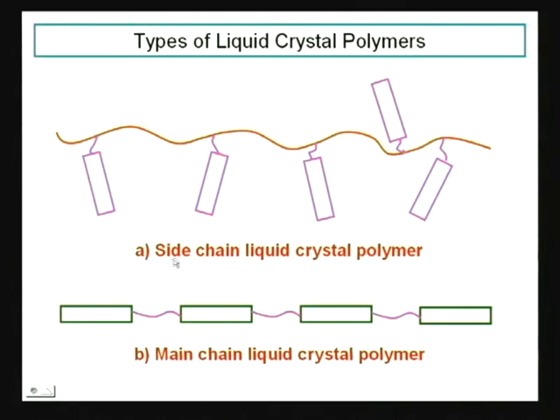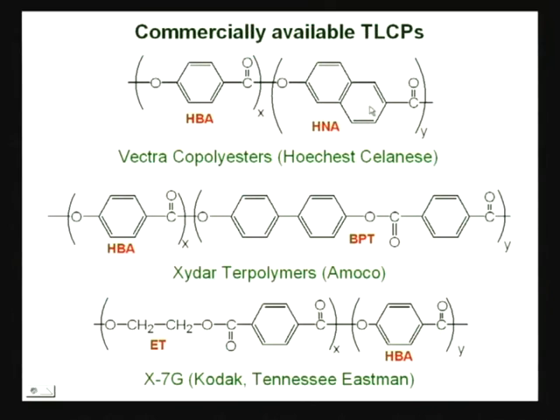Types of liquid crystal polymers, again these are mesogens, as I was showing you, side chain liquid crystal polymer, that means liquid crystallinity is contributed by these mesogens attached to side chains, whereas there is no contribution from this main backbone chain. Main chain liquid crystalline, here these mesogens are in the main chain. Okay. Commercially available thermotropic liquid crystalline polymers: Vectra copolyester, Hoechst Celanese, Xydar polymers, Amoco. You look at these structures, these are commercially available.